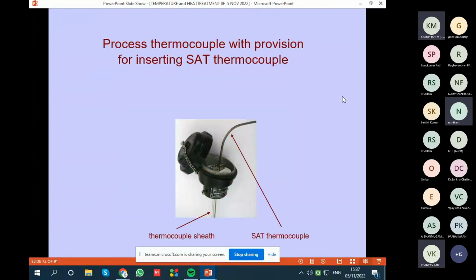This is a thermocouple what we use. A thermocouple what you use and what we put inside is a SAT thermocouple. Either we use this arrangement or we insert another thermocouple inside the furnace very near to your thermocouple, within 50 millimeter distance between the two tips, and compare the results. This is called SAT test.